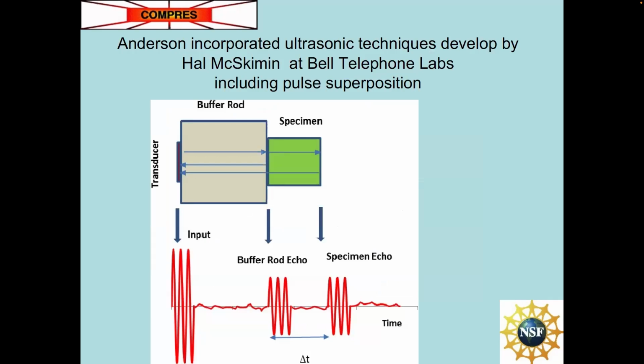So Anderson incorporated the ultrasonic techniques developed at Bell Labs, and basically it's just a question of imposing different reflections of the sample and other interfaces. So you have a piezoelectric transducer of the kinds that were developed during the war to generate an acoustic signal that travels through a buffer rod, reflects off that buffer rod's specimen interface, extends into the sample, reflects off the sample or specimen air interface, and returns.